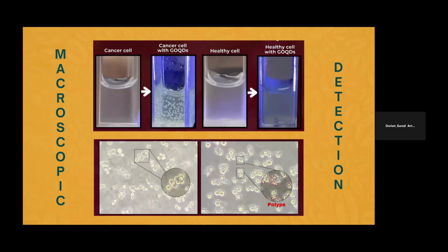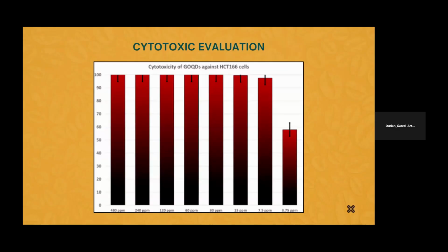But GOQDs don't just detect cancer, they also fight it. In our MTT assay, or our cytotoxic evaluation, GOQDs had an IC50, or inhibitory concentration 50%, of 3.26 parts per million, which demonstrates strong anti-cancer potential. At concentrations of 7.5 ppm, they were able to kill up to 97 to 100% of cancer cells. This happens because the unpaired electrons in GOQDs generate reactive oxygen species. These ROS damage DNA, disrupt mitochondria, and ultimately push cancer cells into apoptosis, or programmed cell death.